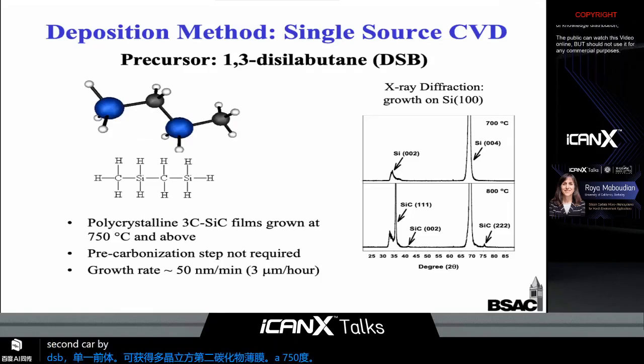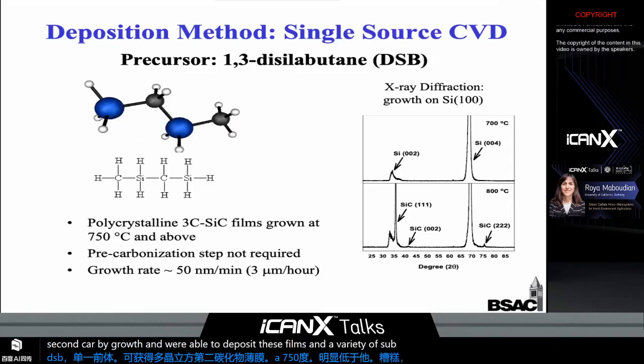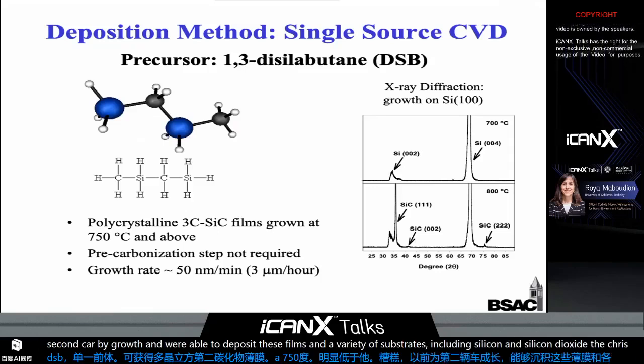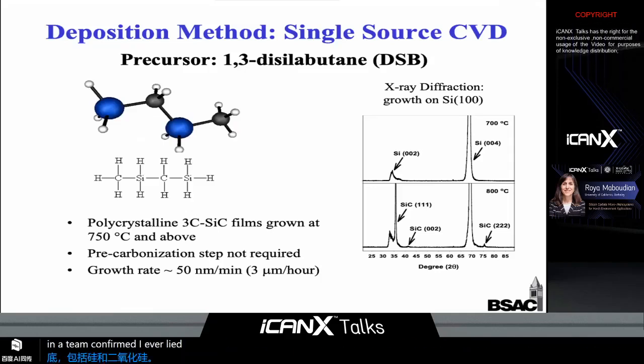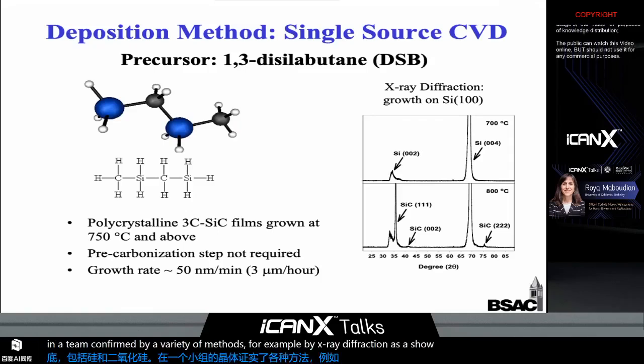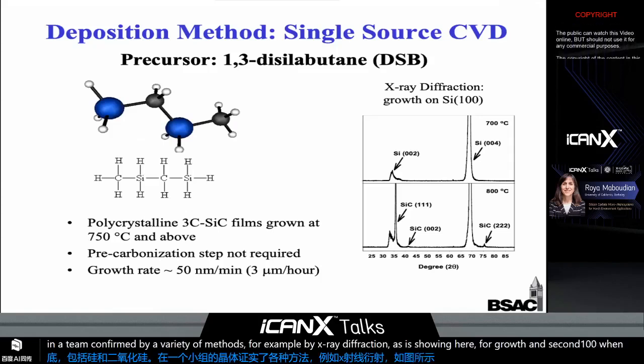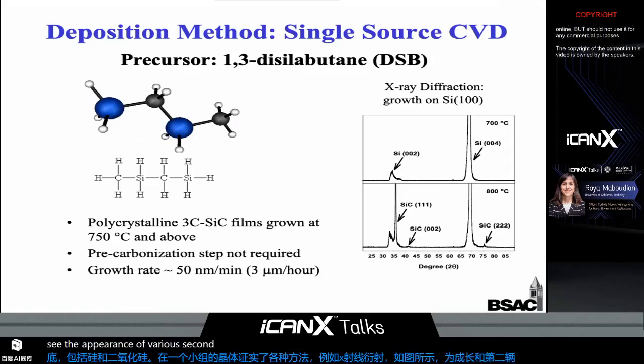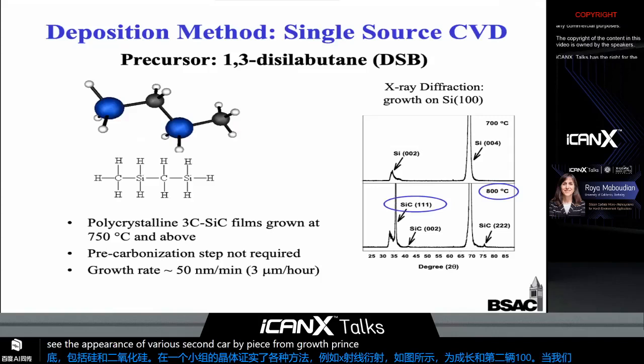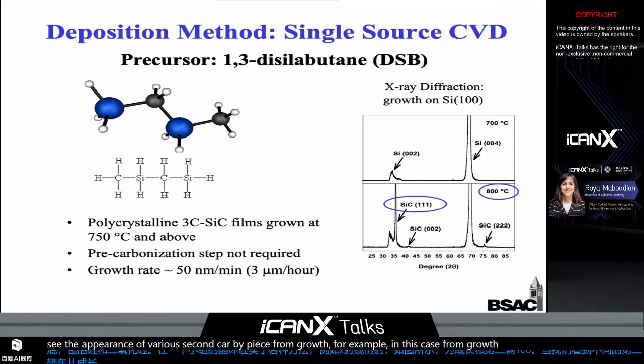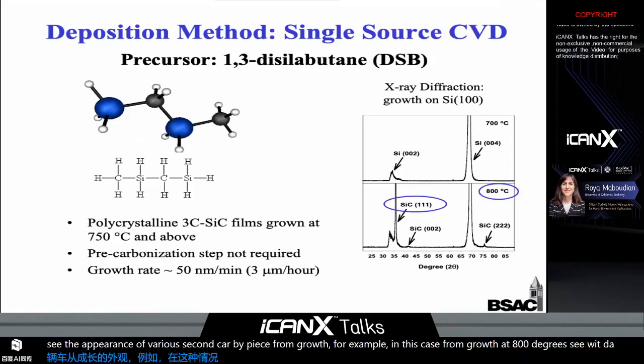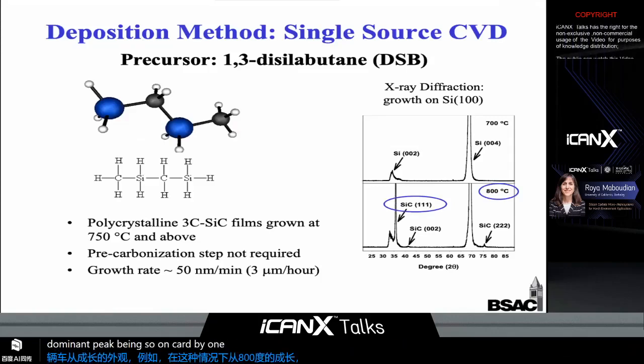And we were able to deposit these films on a variety of substrates, including silicon and silicon dioxide. The crystallinity is confirmed by a variety of methods, for example, by X-ray diffraction, as shown here for growth on silicon 100, whereby we see the appearance of various silicon carbide peaks for growth, for example, in this case, for growth at 800 degrees C, with the dominant peak being silicon carbide 111, suggesting a highly textured film.